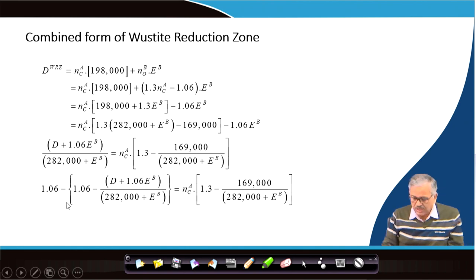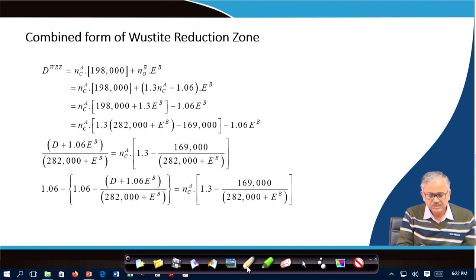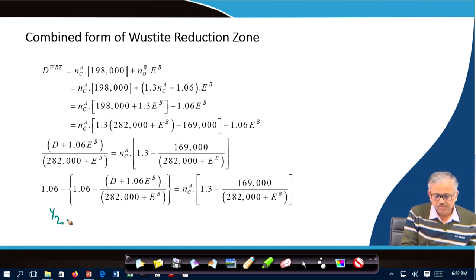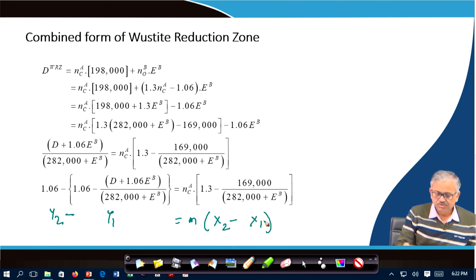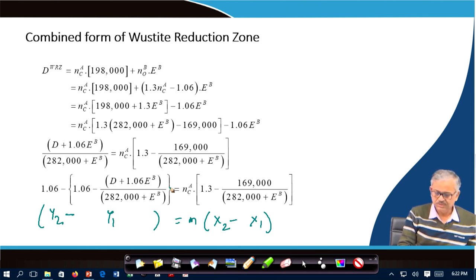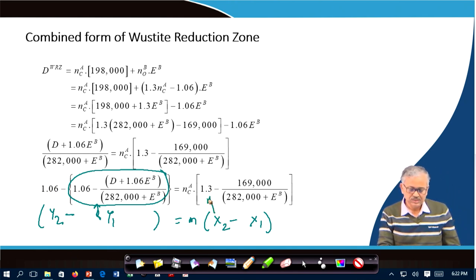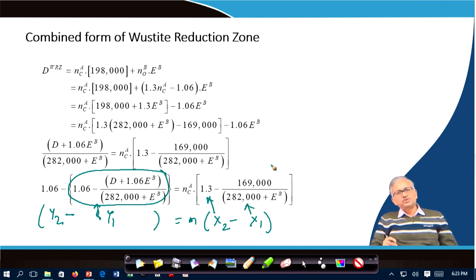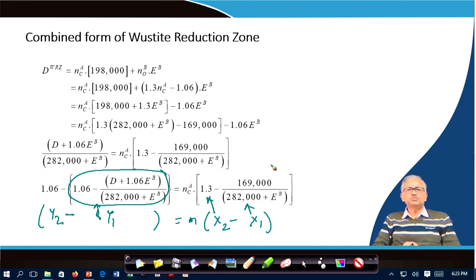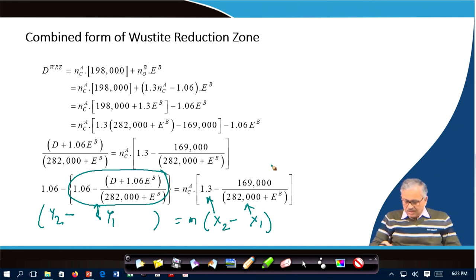After setting demand equal to supply and eliminating O/C between the material balance and enthalpy balance, we get an equation of the form: (y₂ − y₁) = M × (x₂ − x₁). This is a straight line, where x₁, x₂, y₁, y₂ are all defined — meaning there are two fixed points on the operating line. Points labeled A (or W) and B (or H) on the Rist diagram are fully determined.